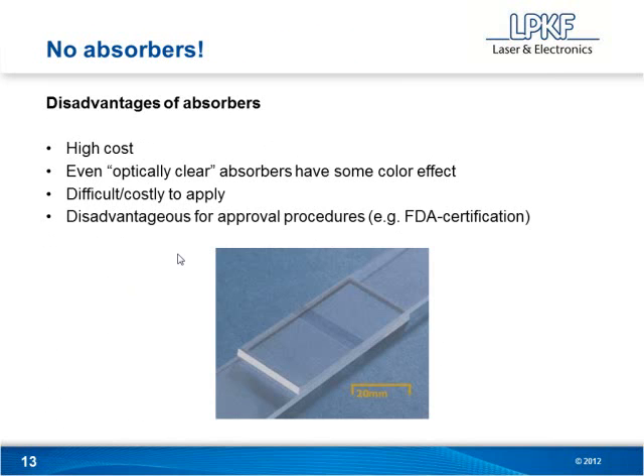So the big deal about no absorbers, one, specialized absorbers can be very expensive. Obviously, if you dope them into the plastic, they're going to be more expensive, but if you apply them locally at the joint, which we see a lot in production before this technology existed, it's difficult to apply and it can cost a lot to figure out how to do that. So now that we don't require these absorbers anymore, the cost of welding 2 clear pieces of plastic is going to be significantly cheaper. And then also on top of that, even though these absorbers allowed the plastic to remain clear, they still had some effect. You would see this greening effect of the plastic.